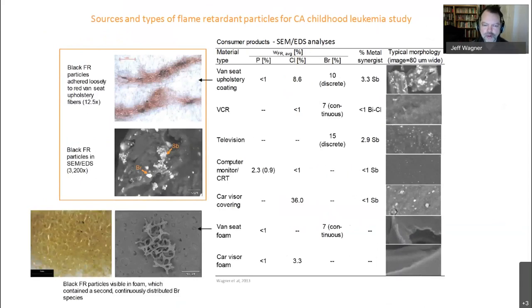It turned out that the upholstery and textile coatings were a good match to a lot of the environmental particles we saw. And that kind of makes sense because these are very friable coatings that you might expect to wear down in the environment over time and distribute their solid phase flame retardants, primarily DecaBDE in our samples. So on the left, you see some examples of these fibers with the black coating. Each of those black polymeric coating particles had within them submicron and micron sized bromine and antimony particles. In some cases, we would see multiple types, such as in the bottom, you see a foam particle.